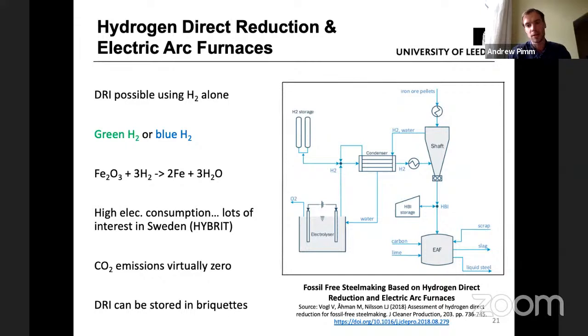It extracts the oxygen and gives you a waste flue gas stream, which is a mix of unreacted hydrogen and steam. Then, as I said, you extract some of the heat from that, separate out the water, and mix what you've got with fresh hydrogen. And you just keep running that. Ideally, you heat the iron ore up on the way in. You have DRI coming out, direct reduced iron. You can form hot briquetted iron, HBI, if you want to store this. Or you can do a hot feed straight into an electric arc furnace. That's the way of minimizing energy losses, because you take advantage of the heat in the iron.